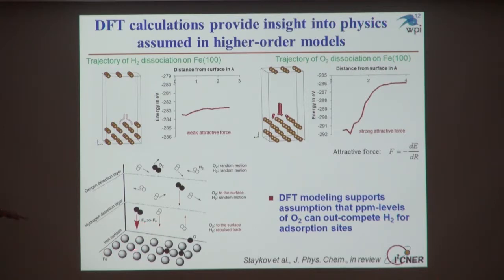And then in the next layer closest to the iron surface, both the oxygen and the hydrogen are sensing the surface, and so they're both going to be drawn towards the surface. But the force on the oxygen is stronger than the force on the hydrogen. And so this is just one possible way that we are getting some insight as to how part per million levels of oxygen can outcompete hydrogen for these adsorption sites.